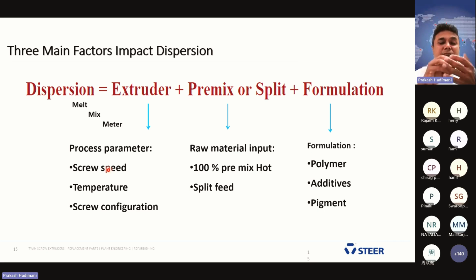When the pigment agglomeration has to be broken down, you need to have a wax and all the ingredients. Again, temperature plays an important role. Your screw configuration also matters. Screw configuration depends on your pigment. You need to adjust the screw configuration. If your pigment is very sensitive and you apply a harder screw design, then you're destroying your pigments. Everybody calls that my pigment started re-agglomerating. It is because of this. If you are applying more pressure, more shear on the particular pigment, how much shear the pigment needs, we need to calculate and then apply.